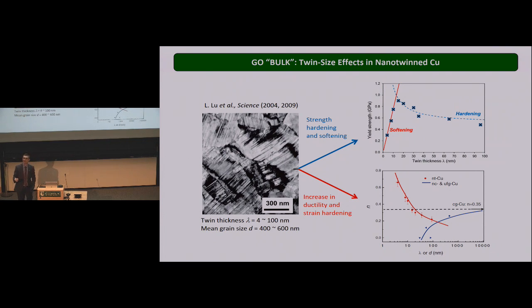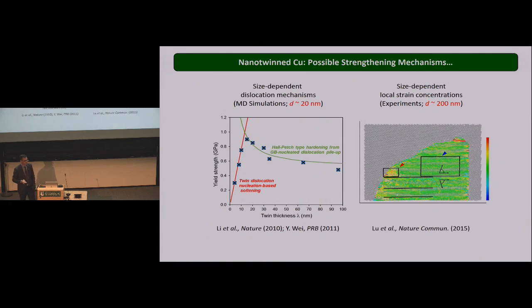These nanotwin metals show a totally different behavior. When you decrease now the twin size in the system, actually the ductility increases. So it's kind of a miracle material where you have both the strength and the ductility being controlled and enhanced by the twin size. So what we're trying to understand is the mechanism behind that.